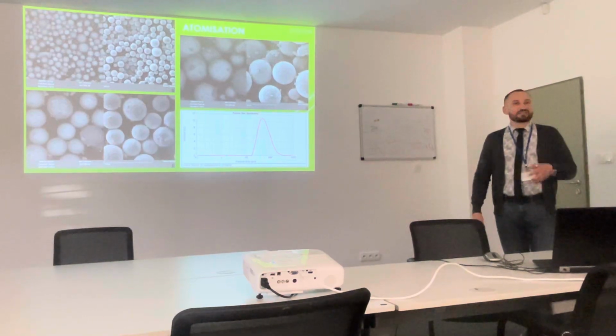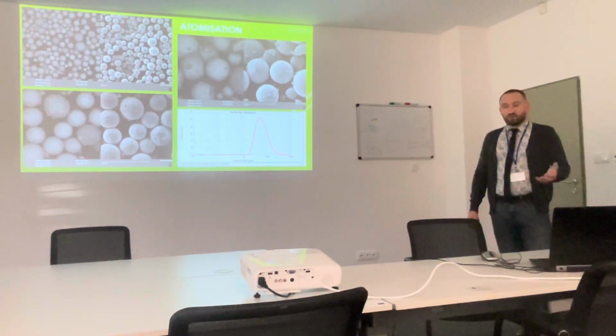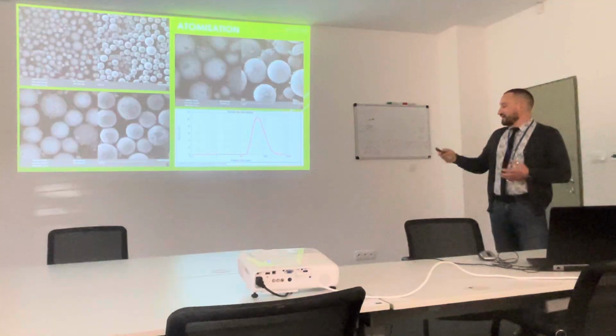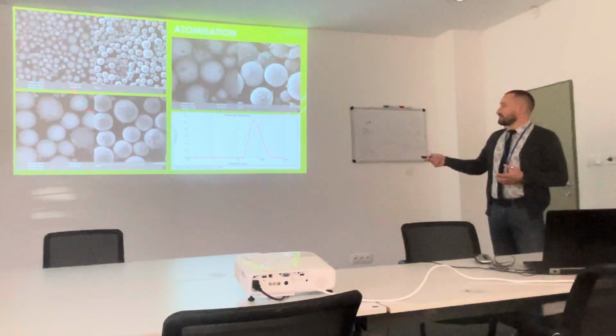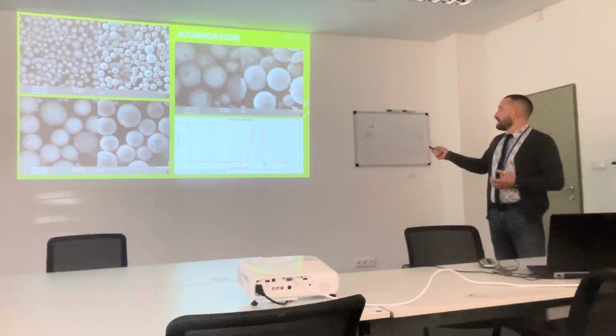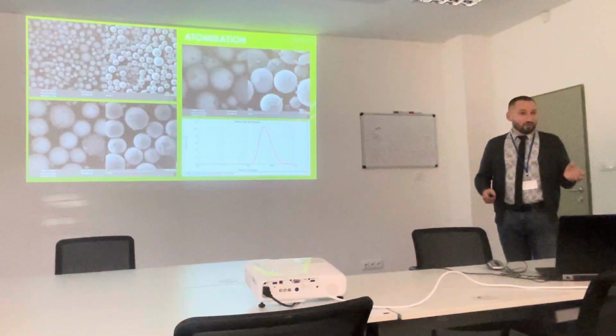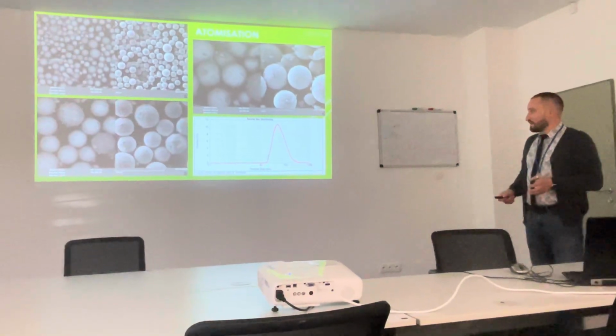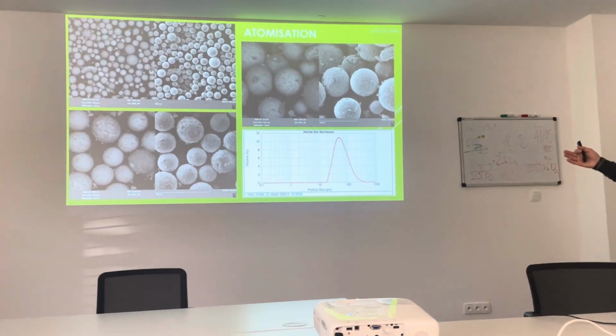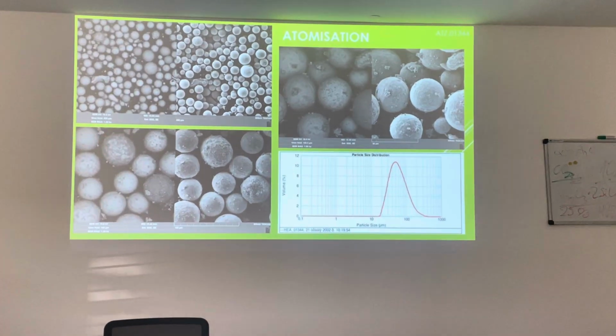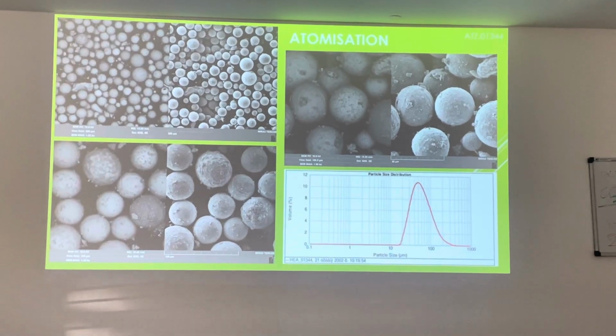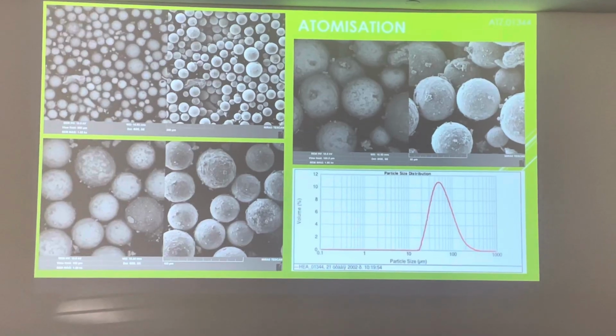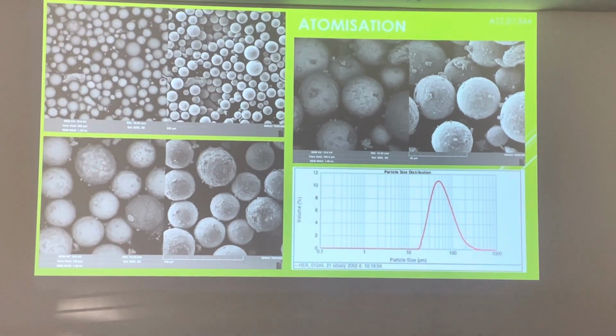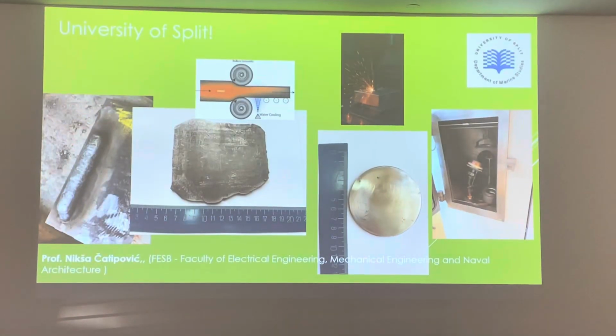Another application of using such filament is atomization. Atomization and obtaining of spherical particles with uniform high entropy alloy composition. And this is a way to use this material in selective laser melting or electron beam melting process for 3D printing actually.